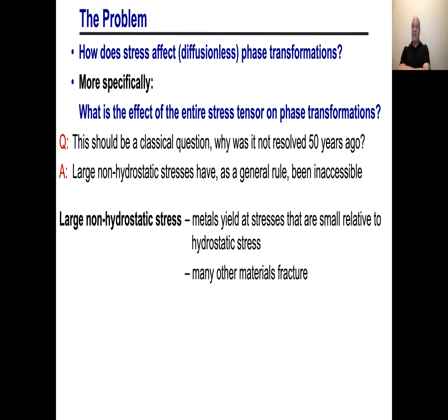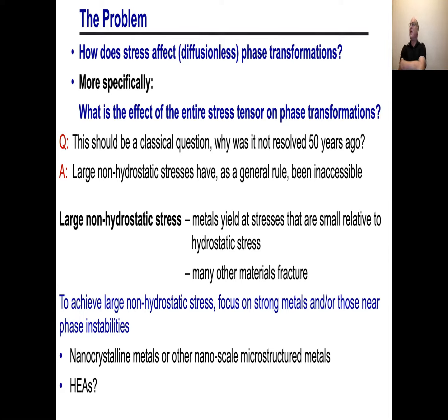So the main issue has to do with the fact that in practice, it's very difficult to put on very large shear stresses. So to achieve these very large non-hydrostatic stresses, what we can do is start thinking about some of the ultra strong, ultra high strength metals, or metals which are near phase instability. Some of the high entropy alloys are near phase instabilities. And in the nanocrystalline metals, like the example I showed you before, nickel, or other nanoscale microstructures, you can really achieve stresses which start to approach the theoretical strength of the material. So you're only going to see these kinds of effects I'm talking about today in metals when you have nanostructured materials or extremely high strength metals or materials which are very close to instability. So there are two ways to do it.